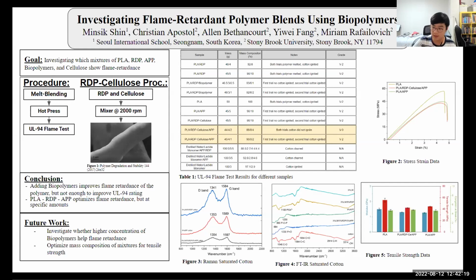So onto the results. There are mainly 3 groups: the one with the biopolymer, one with RDP cellulose, and our flame retardant solution. The one with the biopolymer did not do as well, as you can see. Compared to just PLA and RDP, it did better, as in the first trial, the polymer with the RDP and biopolymer didn't ignite, but in the second trial, the cotton still ignited, so the UL94 flame test grade didn't change. The second group was with the RDP cellulose and APP. Optimizing for the least amount of APP, we found that 88% PLA, 8% RDP cellulose, and 4% APP still yielded a flame retardant polymer with the V0 grade.